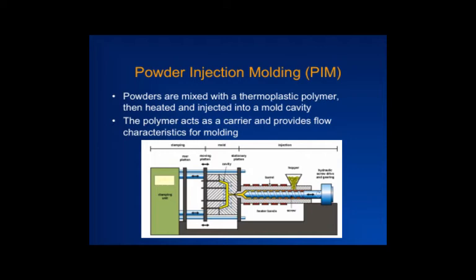We'll look at it in a little more detail, but you have the mold, the clamping unit, and the injection unit. The mold cavity typically has a few microns cut out as a vent. You have a mold, it's closed, there's still air in it. As material comes in, the air can be compressed to a point, but if it's a full seal it's going to remain as an air bubble on the surface. So there are thin gaps cut between the surfaces of the mold — wide enough for air to pass out, but too narrow for material to push through — and then you can push the air out.